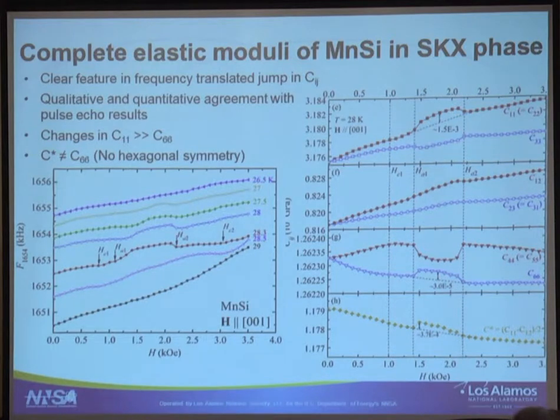And this is important because one of the computational calculations of the stiffening of the Skyrmion says that you should have pretty much the same C11 as the C66. And this is actually very different to what you will get, let's say, in a vortex lattice where the C66 is much smaller. Basically, you can break vortices very easily by shear. Skyrmions should be much harder to break laterally. That's the C66.